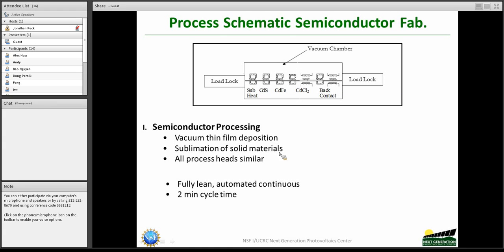The other advantage of this particular process is that it doesn't require a very hard vacuum. Vacuum generated by simple mechanical pumps is good enough. And all the process heads for doing all of this are very similar, and it's a lean automated machine, and the cycle time that we have used is about 2 minutes per station. So it stays about 2 minutes in each case, and in about 15, 16 minutes you have a whole device that comes out except for the metallization at the back.